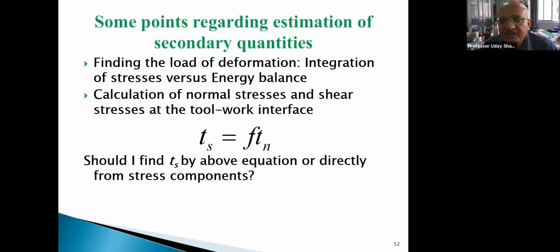It is noted that the energy balance approach will give the correct result, because in one you are dependent only on these surface stresses, and if there is error in the surface stresses, you will get a huge amount of error, whereas in the other you are dependent on the whole bulk of the material. Moreover, when you integrate something, the errors get reduced, and when you differentiate, errors accumulate. Subtraction increases the error, addition reduces the error. Suppose I take 10 data, and in each data there are random errors. When I add them together in the total sum, some errors will be positive and some negative, and the effect will be nullified.